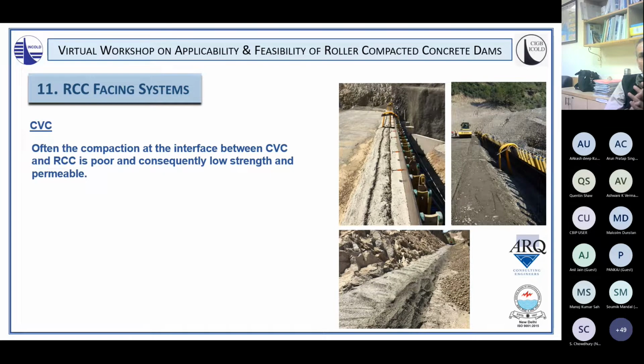Conventional mass concrete. Conventional mass concrete is often used as a surfacing to RCC, and there will be somewhere in all dam structures where conventional mass concrete and RCC interface at some point. Often the compaction at the interface between conventional mass concrete and RCC is poor, and consequently low strength and permeable material exists. Theoretically, a good bond between conventional concrete and RCC can be achieved when both are compacted simultaneously. However, the reality is that this is very difficult to do, and it's an ambitious objective to actually achieve. It interferes with construction quite considerably.